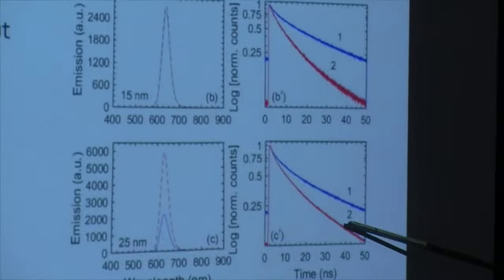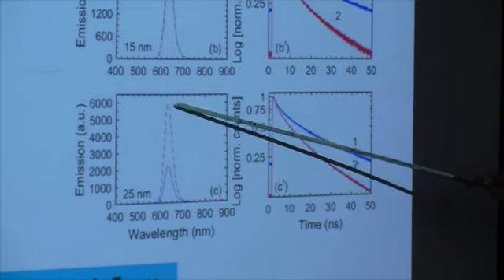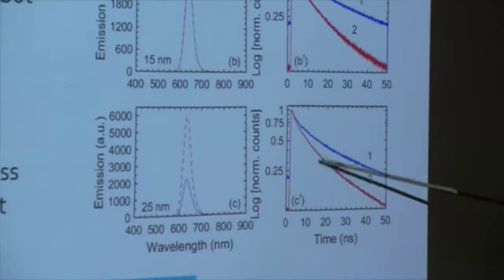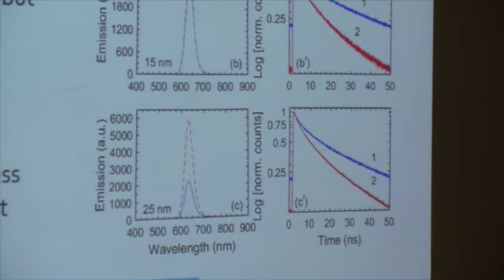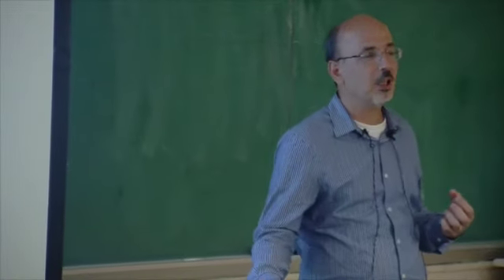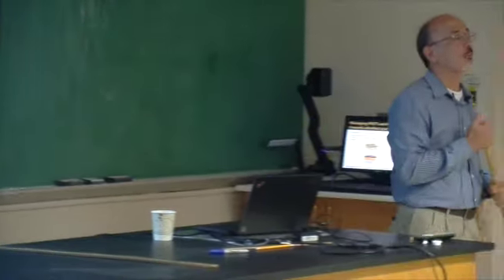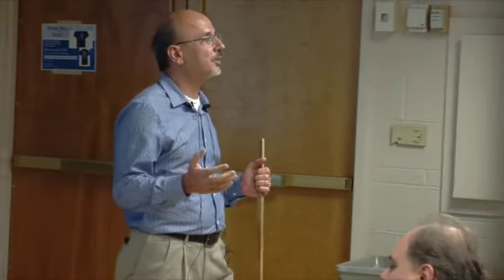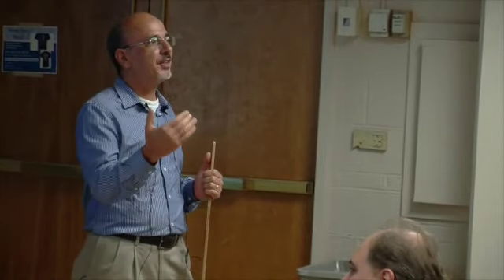All the time, the emission of the quantum dot, although intensity is higher on the metal, is long. You can see it's about 10 nanoseconds. If you talk with many people in the device field, they don't like 10 nanoseconds because it is very long. People like to go shorter, and they make very complex structures to make it shorter and shorter. So what I'm going to show here is that we play around with this and make the lifetime an order of magnitude shorter, but the emission does not change. So we deliver the same amount of intensity, but we make the lifetime extremely short.